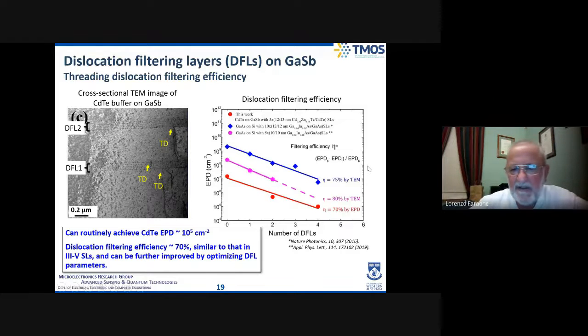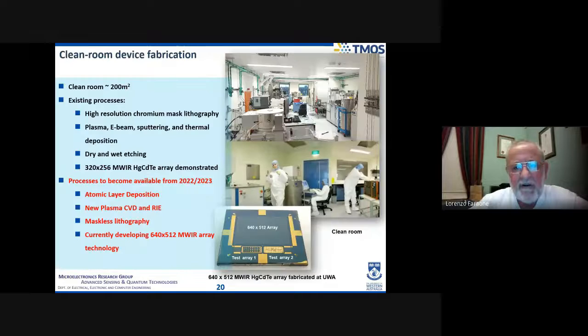So as I said, this is still sort of unfinished. There's some work here from other people on growth of gallium arsenide on silicon, and this is our work for cadmium telluride on gallium antimonide. You can see very similar trends, very similar behavior. But 10 to the 5 is still not really good enough.